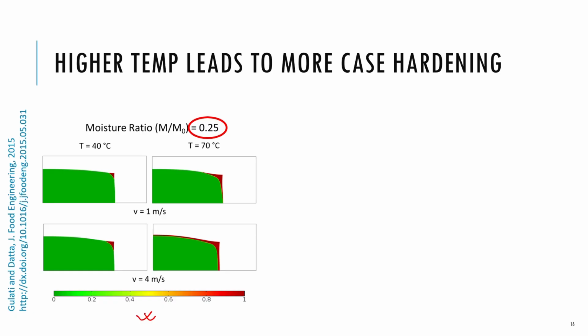At this early time, at the higher temperature or faster drying, there is a thin crust forming on the surface. Since the moisture is low in this dried thin outer layer, the glass transition temperature for that layer is very high, much higher than the actual temperature, making the material glassy.